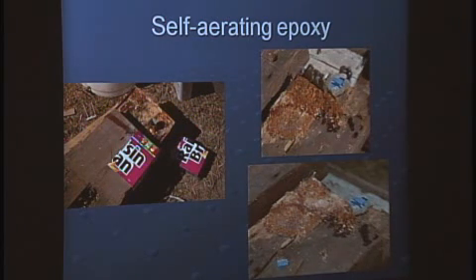But if I had achieved only an epoxy reconstructed element there that was the density of the epoxy, it would have been so hard and so dense it would have almost certainly fractured as soon as some number of stress cycles were placed on it. But in fact, because I got this to boil, it actually aerated itself. So it is an epoxy foam. It is a wood, well, I don't know if it's an impregnated epoxy or impregnated wood, but there is this mixture of wood shavings with aerated epoxy foam all in one.